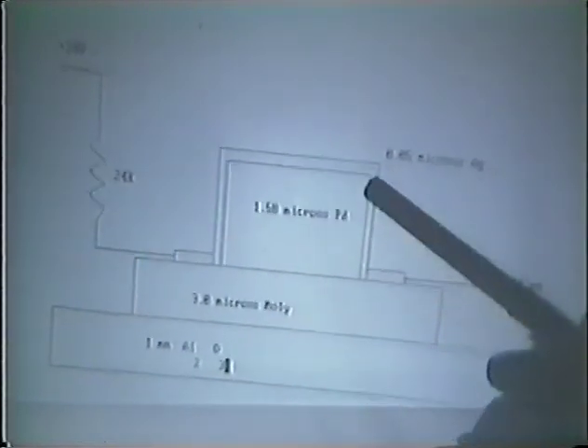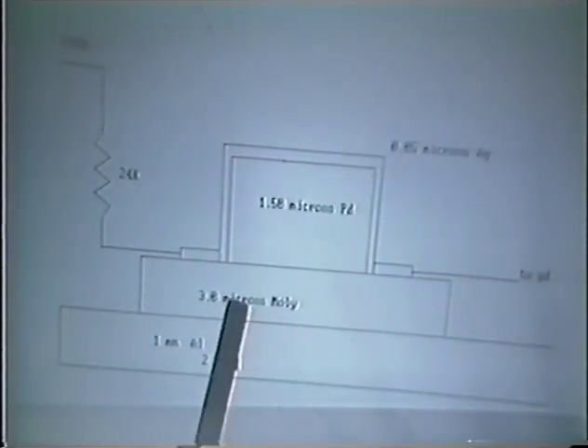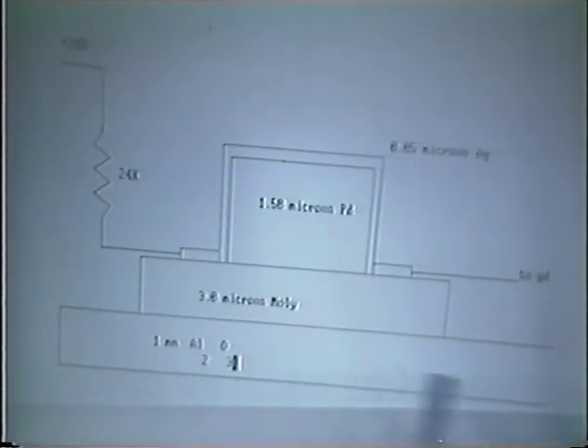Target was prepared, it was deuterated with the beam, energy spectra were measured, and control spectra were also measured. The target was prepared by the evaporation method at the Solar Energy Research Institute in Golden, and consisted of about 1 square centimeter wide foil by 1.5 microns thick. It was on a 3-micron moly backing, which again was on a thick alumina backing.